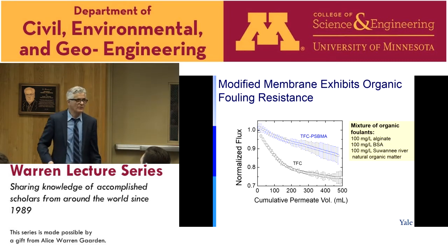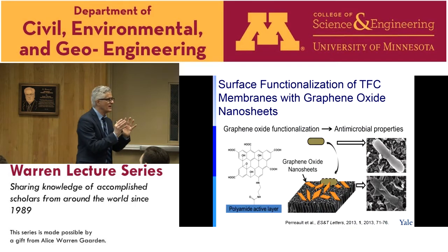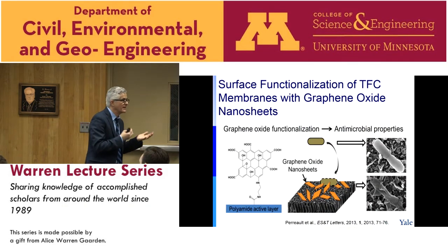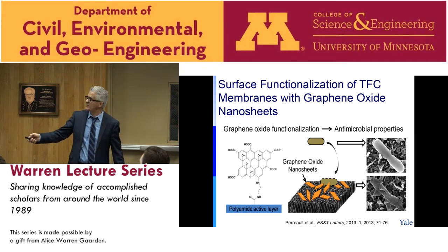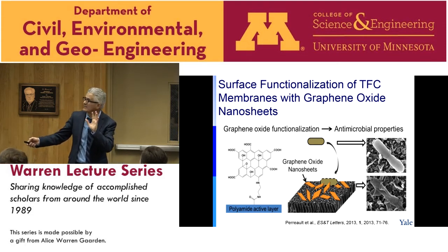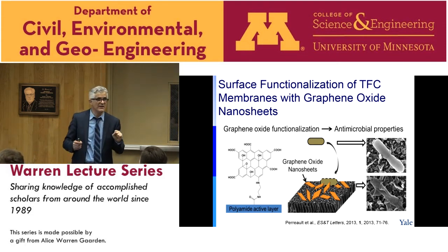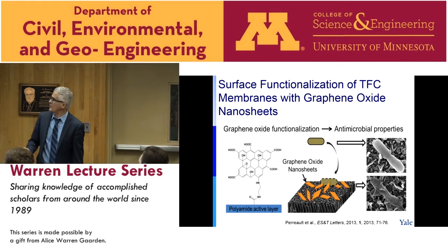We also do some work with graphene oxide. We found that graphene oxide is antimicrobial, can kill microbes. So we developed a way to bind the graphene oxide to the membrane. Then you can get these graphene oxide nanoblades, more like that, that can kill the microbes by a combination of physical and chemical oxidation mechanisms. Now let's go through the detail.